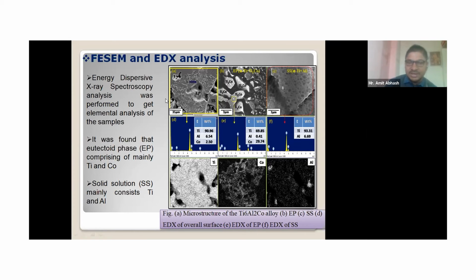This is the first diagram, A. These are the phases formed after sintering. This is the eutectoid phase, and this remaining part is the solid solution phase. If you go through some of the literature, you can see this is the generalized structure of the eutectoid phase. And this is the Ti2CO lamellae. This is used as a coating element, so this will definitely increase the life of your implant. And this is the solid solution of alpha titanium and aluminum.